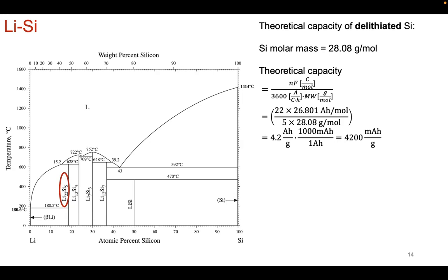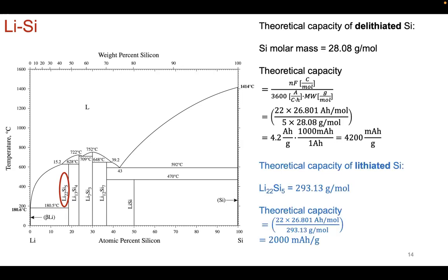So that's converting and alloying 22 lithium with 5 of silicon. Okay, so that stoichiometry is taken into account there. But the reality is, if you think about the lithiated compound and you calculate the theoretical capacity based on the maximum number of lithium ions, which is Li22Si5, the molar mass there is 293.13 grams per mole. So if we take that into consideration, the theoretical capacity based on the lithiated compound is actually 2,000 milliamp-hour per gram.